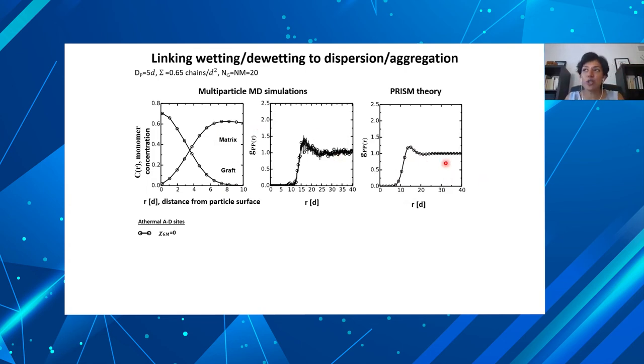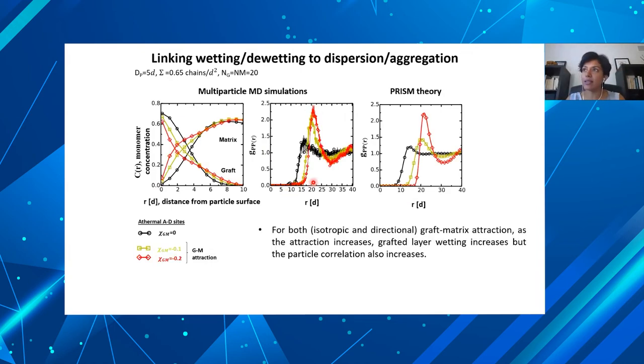So this is at that entropic limit. You already saw this plot. So now let's make it more attractive. And you see, as you make it more attractive, something opposite to your intuition is happening. I told you before, when things wet, particles want to disperse more. But now I'm seeing that the particle-particle correlation has a higher peak. So there's more correlation among the particles, but at larger distances. So keep that in mind, a little bit more attraction, you get the same. And this is not a function of simulation or theory, you're getting the same trend in both methods.